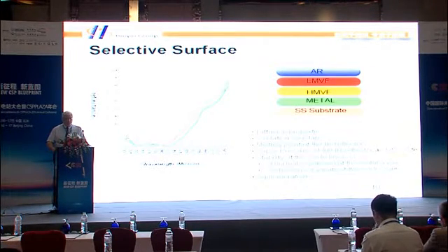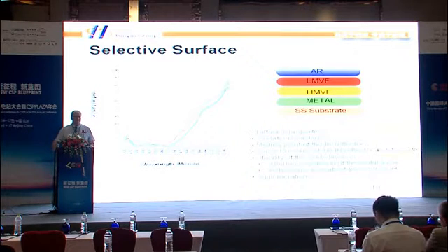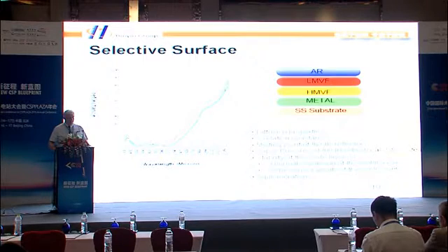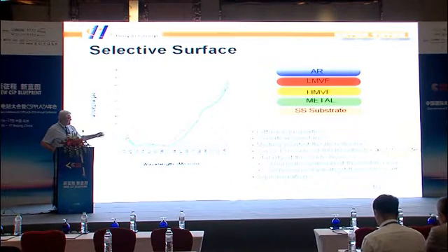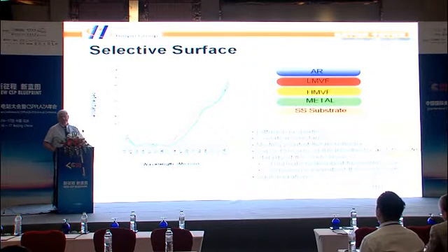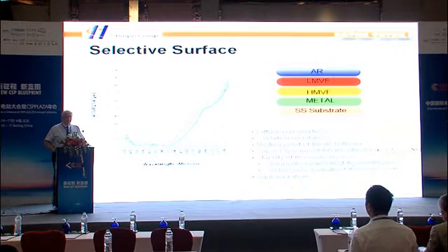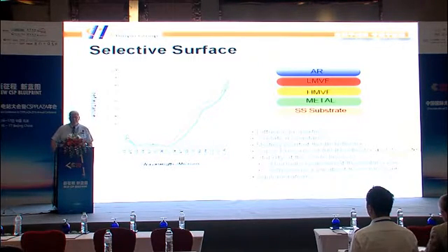And so what we can do with the selective surface is optimize it for a certain temperature range. And you see this optimization in the graph. You see that if we make it thinner, the absorption will go a little bit down. We might go down from 95.5 to maybe 95. But we can also lower the emissivity. So there is an optimization to be done in the selective surface if you go to higher temperature. There are limitations with the technology.